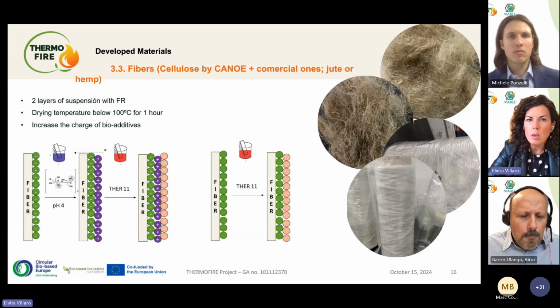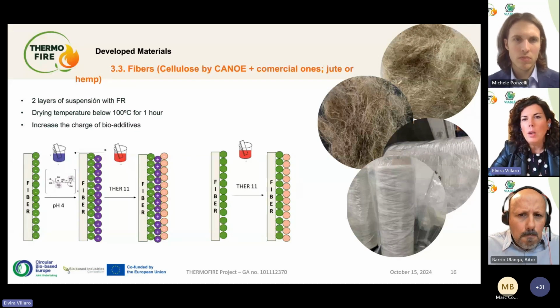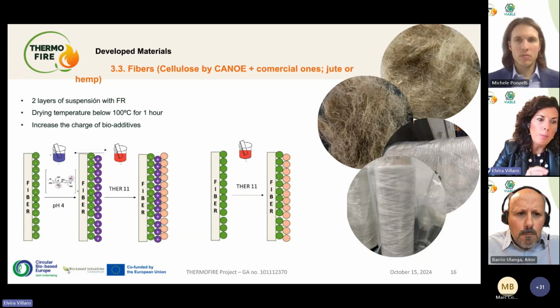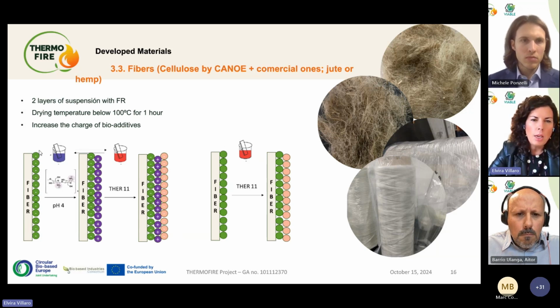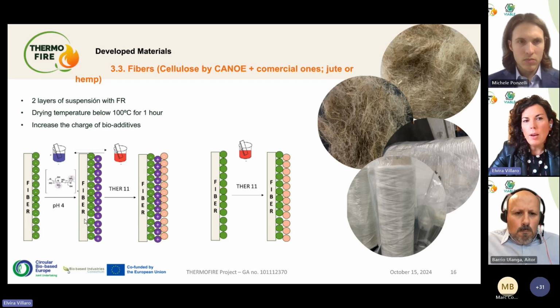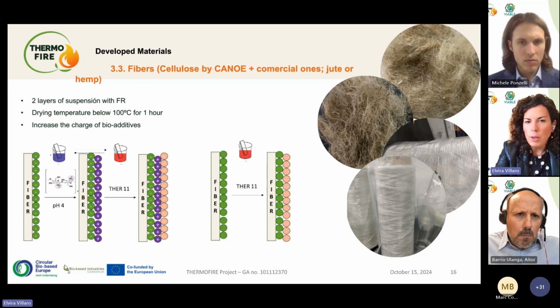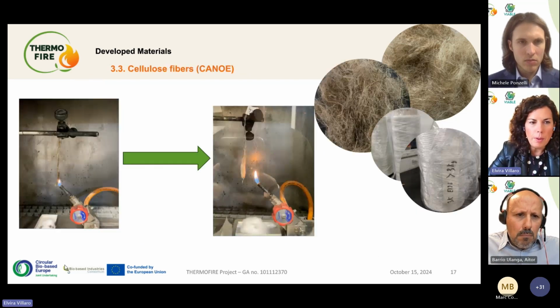So we are using cellulose, which is being developed by Canoe, and other commercial fibers such as jute or hemp. What we are doing is a layer-by-layer process in which we put some layers on top of the fibers. It's very important, as you see here in this scheme, the polarity and the pH in which we are working, to obtain very good adhesion and very good stability of this layer of flame retardant. So we have developed special additives and a special system to have good adhesion of the coating to the fiber. If we compare here, this is a treated fiber and this is a non-treated fiber.